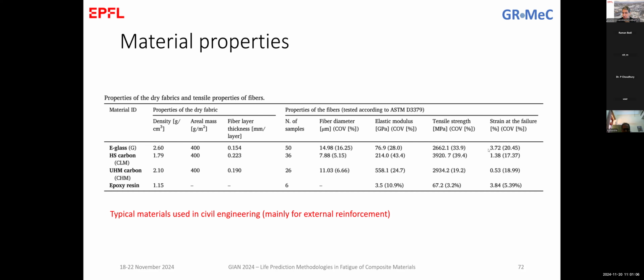But the strain at failure is 2 to 4 or 5 times more than the strain at failure of the carbon fibers, and it's similar to the strain at failure of the epoxy resin, to have compatibility between them. These are typical materials used in civil engineering, mainly for reinforcement of concrete. So these are strips that are glued on concrete slabs to reinforce.